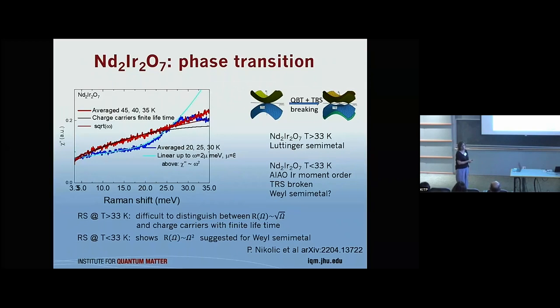Right. So to be honest, there is a little bit of a thing here, and this is something which I would like to understand, so I'm being very honest here. We see this cutoff of the chemical potential in the low frequency, low temperature regime. We don't see this cutoff of the chemical potential in the high temperature regime where we have quadratic band touching. So at this point I'm thinking whether it could be that the splitting doesn't happen exactly at the level of the chemical potential, or we are not sensitive to it. There are two things.